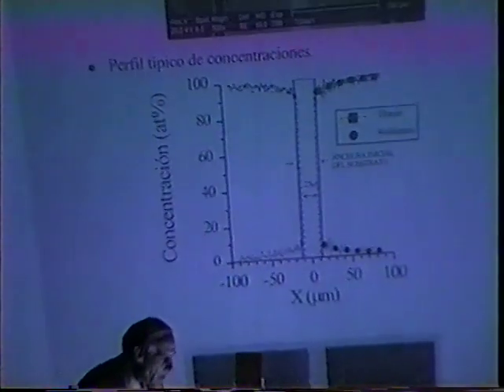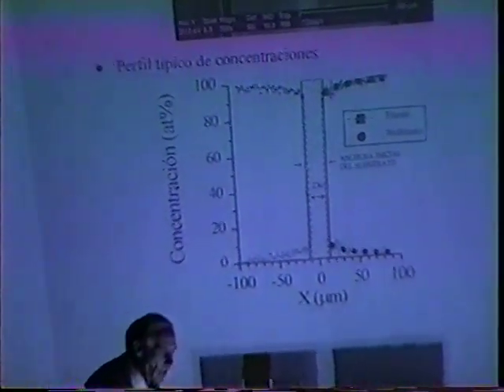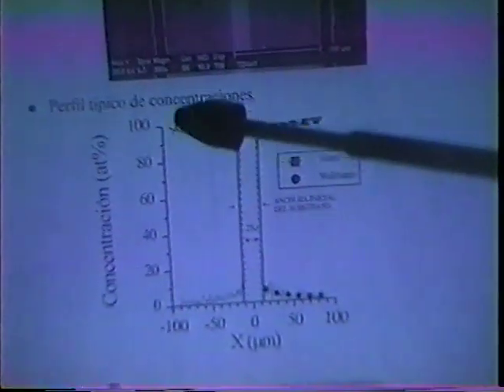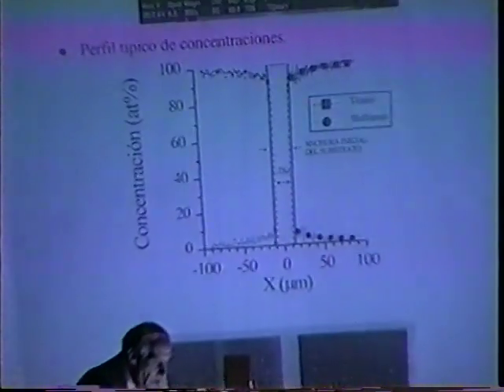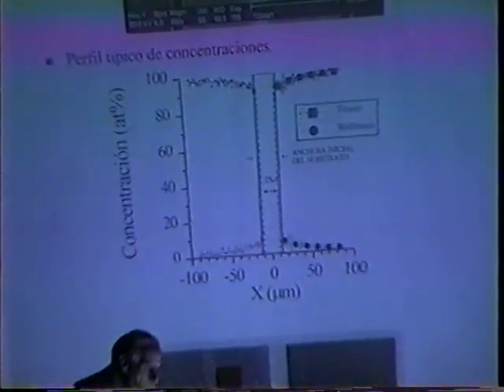We didn't find any metal contamination except that coming from the substrate. There is a diffusion of the tungsten into the titanium, and these are some profiles. This is the titanium profile, and this is the tungsten profile. You can see here the cross sections. This is the tungsten, this is the titanium. An alloy, titanium tungsten, is produced; you can see here this is the tungsten, this is the alloy ring, and this is the titanium ring. So we finally grew the titanium at a low temperature in order to avoid the tungsten diffusion into the titanium.